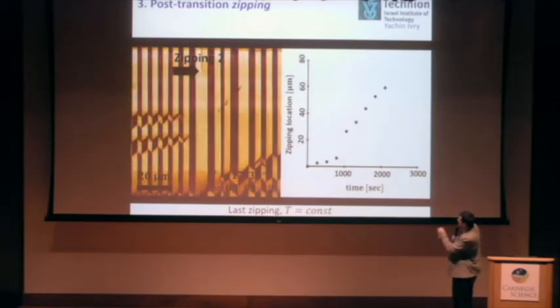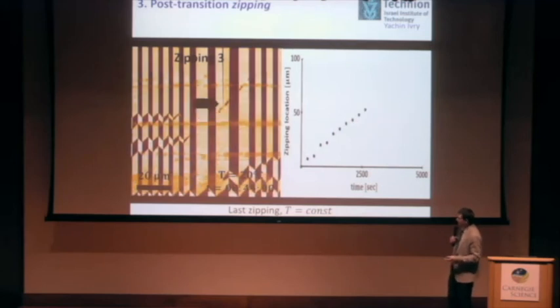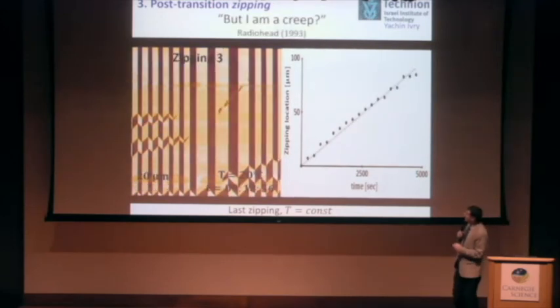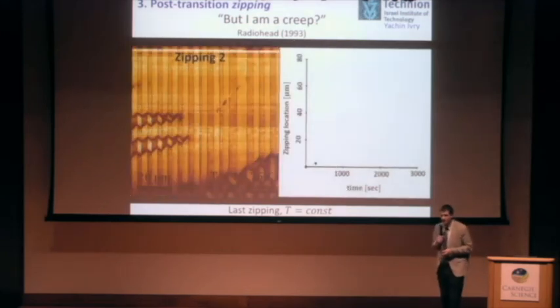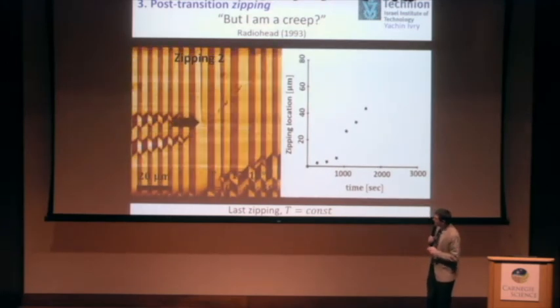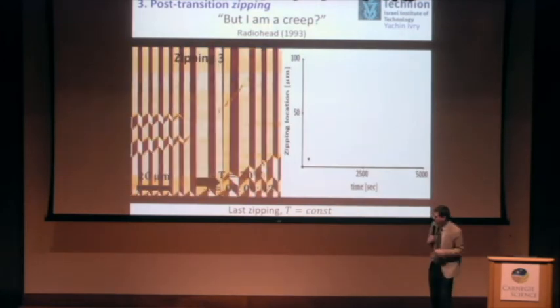And if you look at the rate, for those we saw, they are kind of linear. The first one was very fast, the second one was slower, and then gradually even slower. So this is a slow process, or actually the rate changes. And if we bear in mind what it should be, maybe we expected to have some creep, and it still can be, because if you remember, creep is about the exponent about unity, and we have some kind of distribution. So it's not contradicting that, but anyway, we see that each of these events is nearly linear. This is how it behaves.